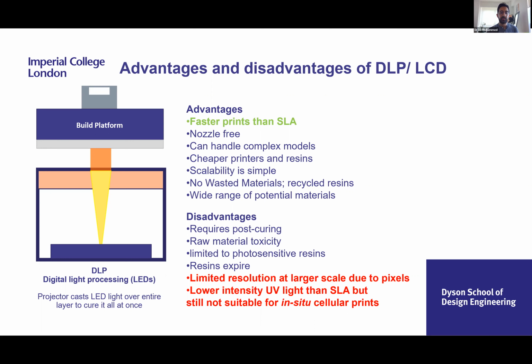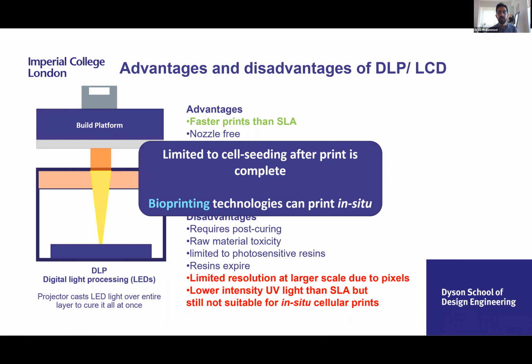And again, although this is a lower intensity UV light due to less energy being used, it's still toxic to cells because an SLA process is very quick. However, a DLP might shine its light for a longer time per layer and can also cause damage to the cells if you're trying to print in situ. So, quickly to summarize, it's limited to cell seeding after the print is complete. So you can create your scaffolds for bioengineering and tissue engineering applications, but you have to put your cells in after.